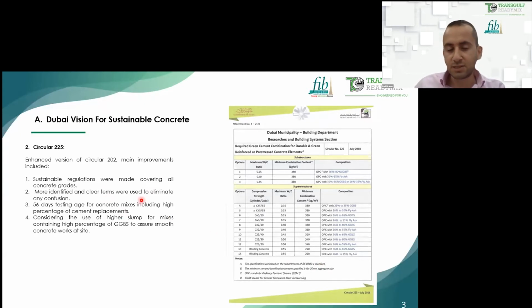Moreover, regarding the enhancement of this circular, more identified and clear terms were used to eliminate any confusion, and 56 days testing for concrete mixes, including those with a high percentage of supplementary cementitious materials, is allowed. It also considers the use of higher slump for mixes, especially those containing a high percentage of GGBS, since this mix is cohesive and shows difficulty in pumping and finishing.